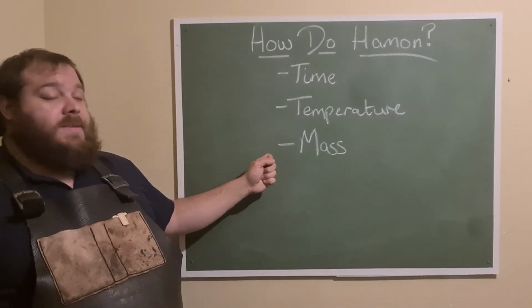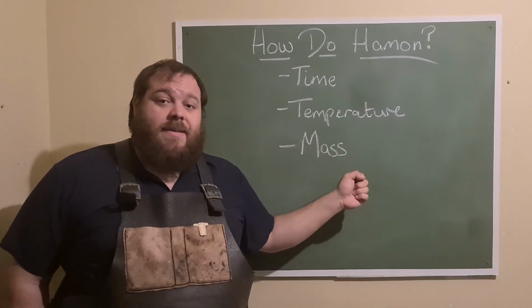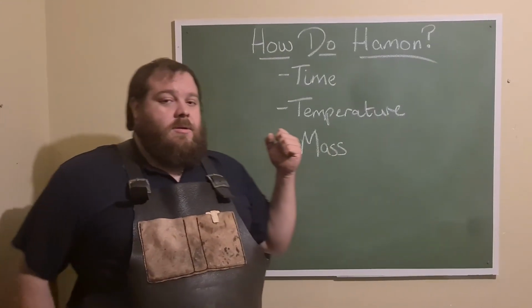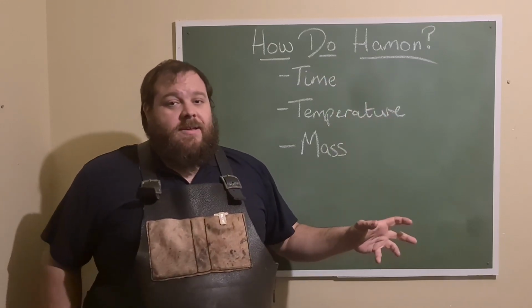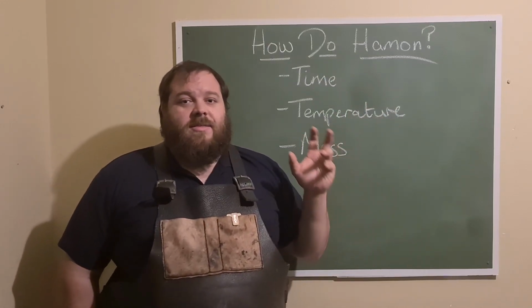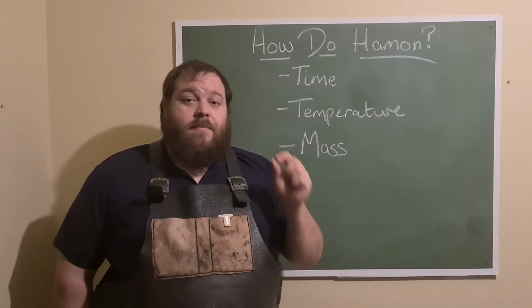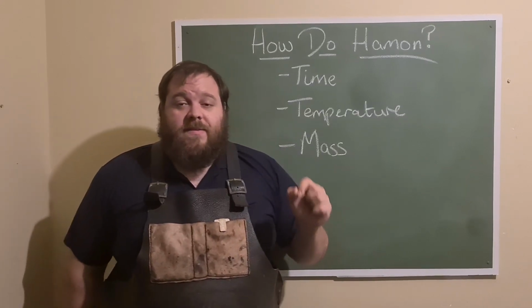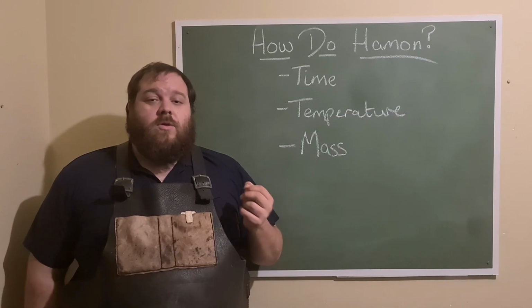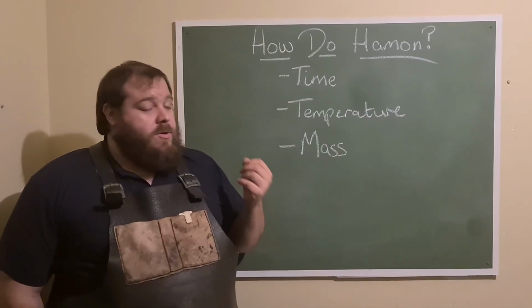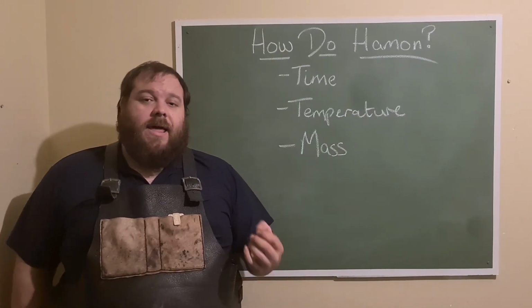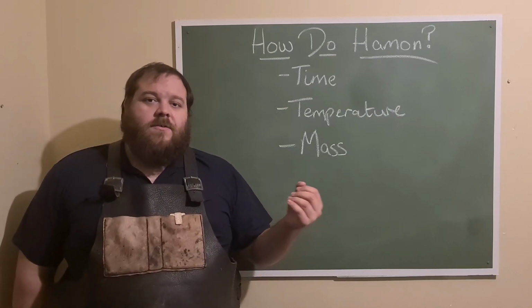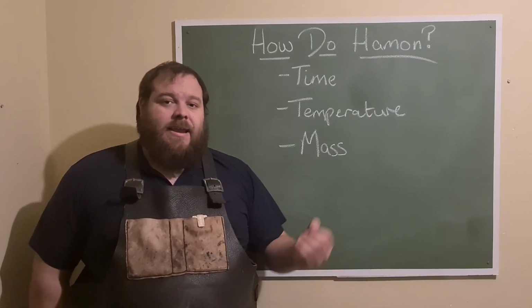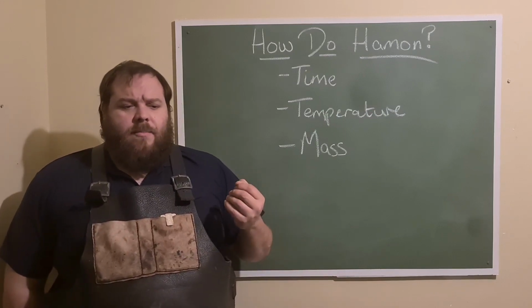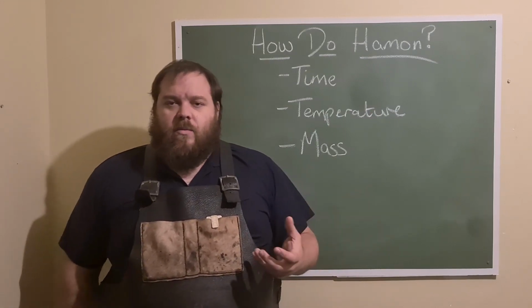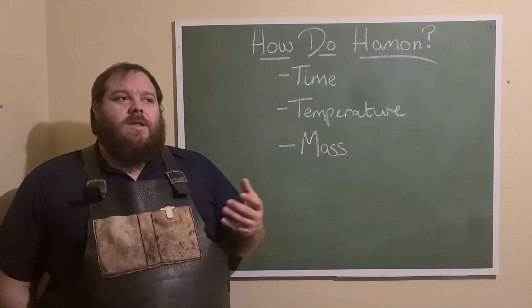The last point is the most important, and that is mass. Now, you can futz with everything else, and you will end up with somewhat of an okay Hamon, but mass is what's really going to trip you up. And this is why we end up using clay in order to create Hamon. When you quench with clay on the spine, the clay is not protecting the steel from the heat. What it is doing is containing the heat. Some people believe that it's actually insulating against the water or the quench media. That's not entirely the case.